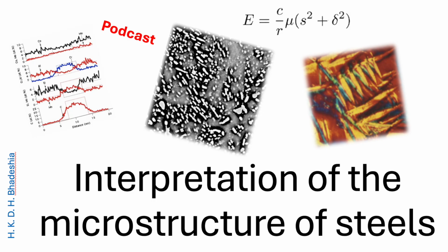So if we're in the lab and we see a sample with this confusing mix of phases, how do we use this framework to identify them quickly just with an optical microscope? The first, most powerful tool is always the morphological rule, the one derived from the atomic mechanism. Look at the boundaries. Martensite and bainite plates have straight, sharp edges, and they are strictly confined within the original austenite grains.